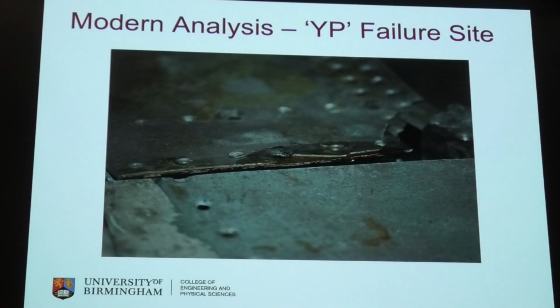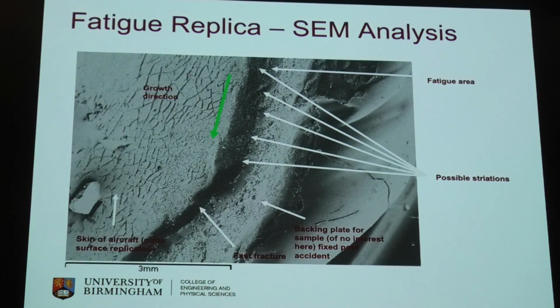That's taken from the photo. That's the actual crack initiation site, and I was honoured enough to actually get down there. This is a replica, a plastic replica of that surface. And you can see the two rivet holes. You can see those pushed through, and if you look under the little flap there, you can see exactly where the crack ran along the edge.